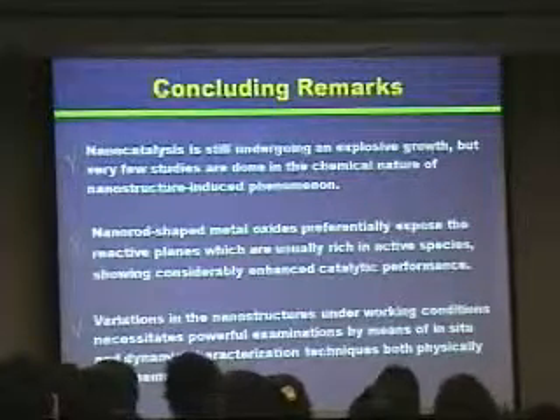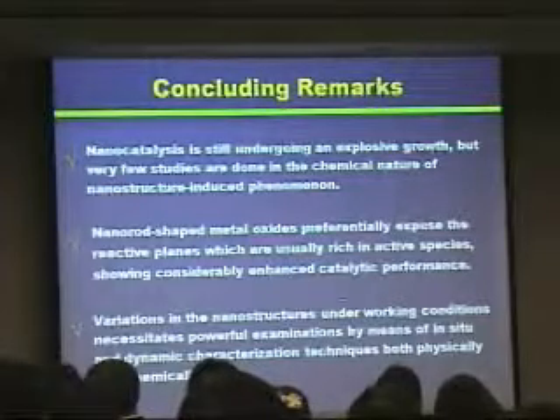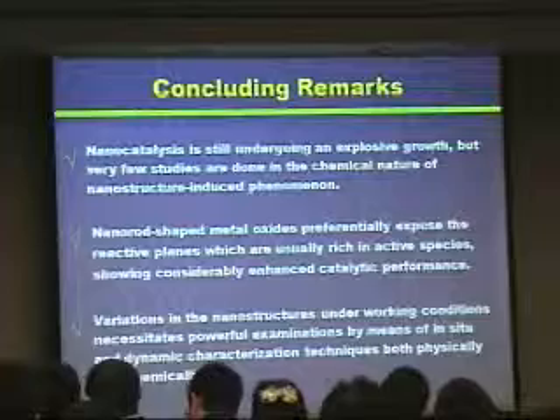So I can conclude like this: nanocatalysis is still a hot topic, but much work has been done on particle size, and I should emphasize that the shape of the metal particles or the oxide particles can also affect the catalytic performance significantly, at the small nanoscale level. Also, another problem that should be solved is those nanostructures, even the size, shape, interface. How about their variation under reaction conditions? They should be rather different from what we observed from the existing ones, not under reaction conditions. So if we can get some information under reaction conditions, that will be more useful for us to design or fabricate new efficient catalysts.